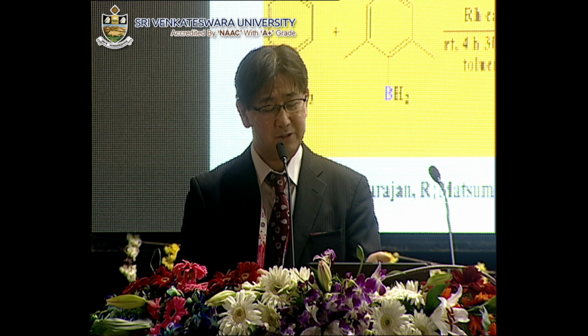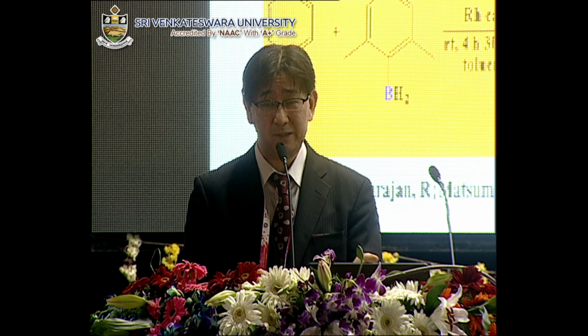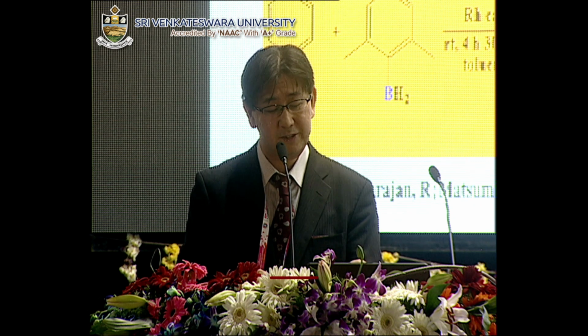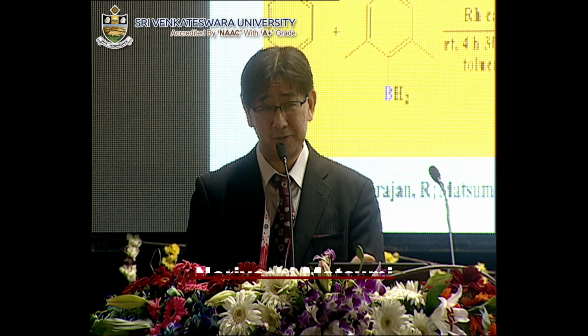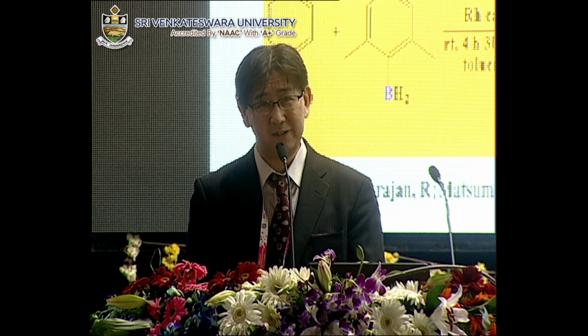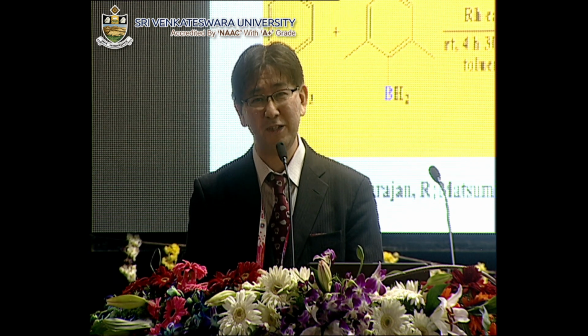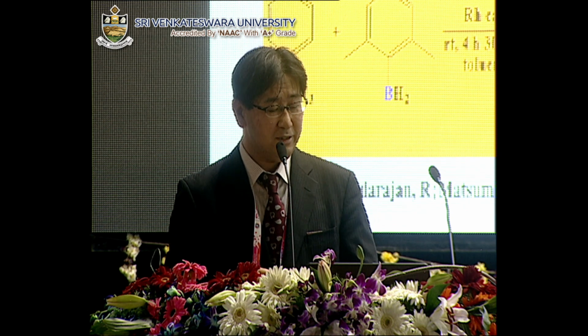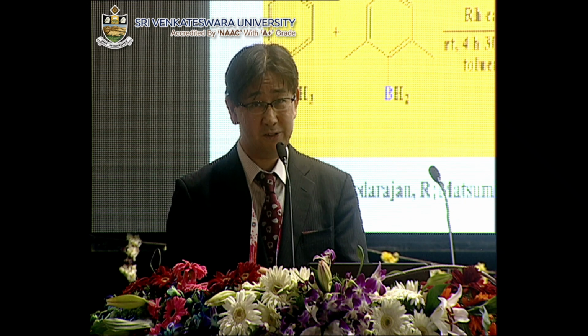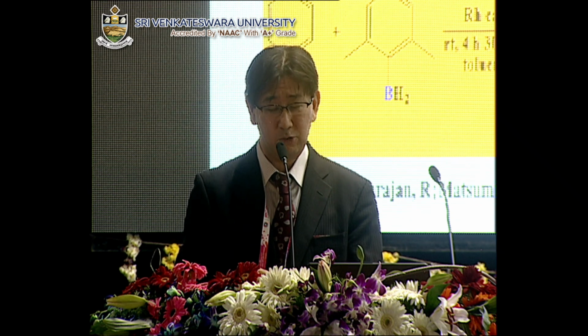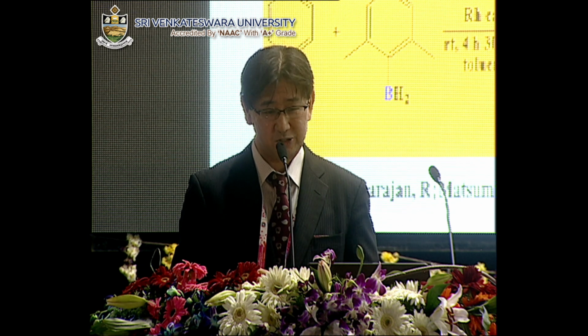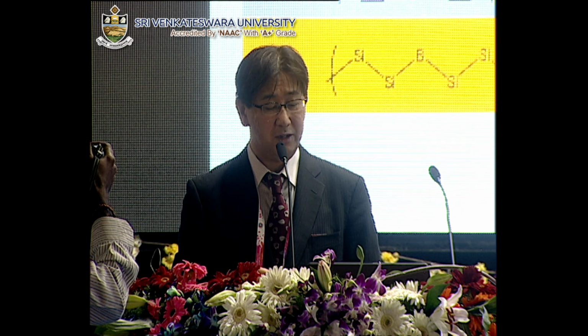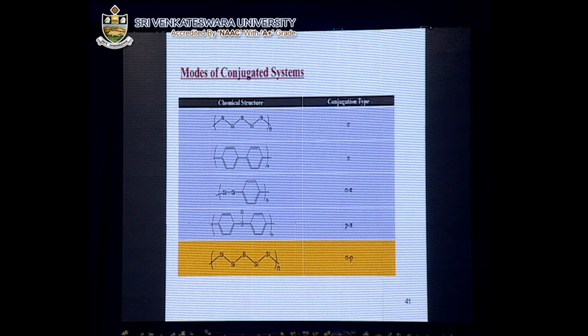After that, we also developed an organoboron polymer electrolyte, and this second material showed a lithium transference number of 0.89, which as far as we know is the highest among anion-trapping type electrolytes ever reported. And here I'd like to introduce another interesting material based on a new mode of conjugation, that is sigma-p conjugation. So far, many kinds of conjugated systems are known, like pi-conjugated, sigma-conjugated, sigma-pi conjugated, and sigma-p-pi conjugated systems. Here, sigma-p was developed by us for the first time.